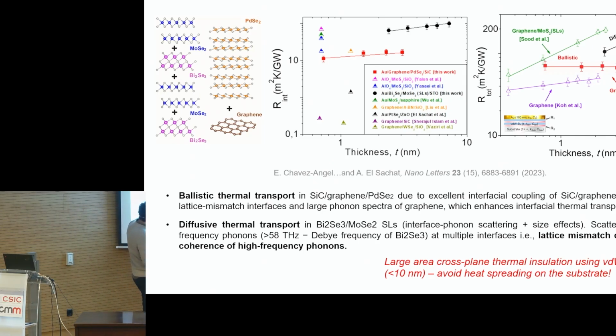The first graph is the interface thermal resistance that we measure. And this consists of two different components. The interface thermal resistance of the transducer that we are using with the film, and the interface thermal resistance between the film and the substrate, R1 and R2 that I explained a bit before. So this is the R interface, okay? And then we go to the R total. The R total is the R interface that we have here, plus the thermal resistance of the film itself.